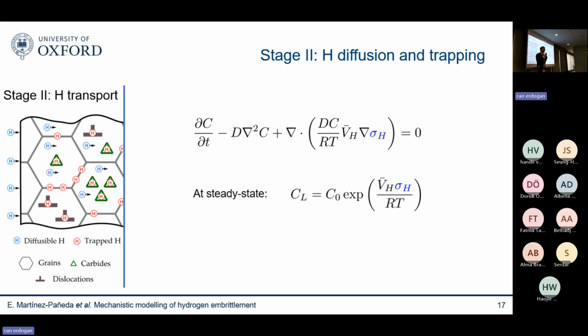And again, strong coupling with mechanics. This is a very important mechanical problem. So you can see, in fact, if you solve this equation for the steady state condition, you end up with a situation where the hydrogen concentration depends on an exponential term, where again you have the hydrostatic stress. So the hydrogen concentration is going to be very high near cracks and other stress concentrators. And this is only part of the picture.